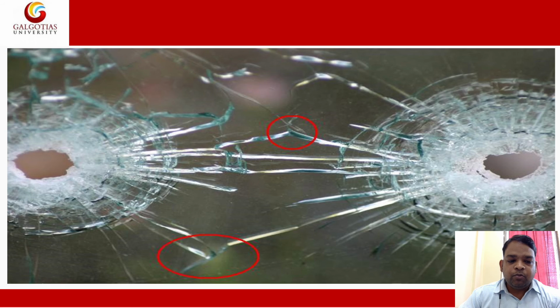When there are several bullet holes, analysis can determine the sequence of the impacts. The first shot will cause fractures that simply run out wherever the original strain has been sufficiently relieved in the material. The radial fractures associated with the second shot will run out when they meet the network of fractures from the first shot, and so on for all subsequent shots.